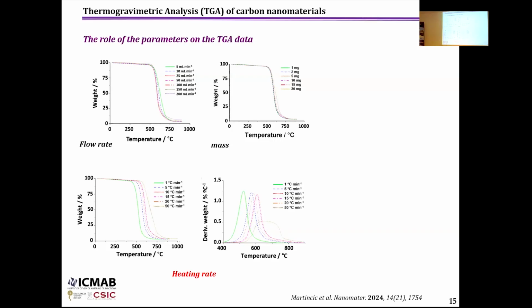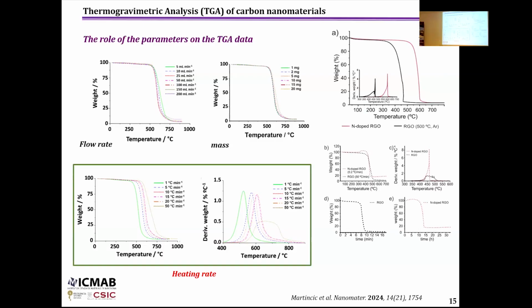This could be because, of course, there are internal processes which are also exothermic during the system. So we need to be very careful when determining the conditions we will use for characterizing these materials. This was also extrapolated to the determination of the thermal stability of graphene oxides in order to see if this is reproducible. So we observed similarities in the measurements and the effects of the heating rate in the measurements using TGA.